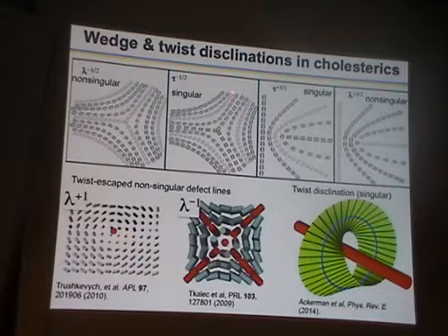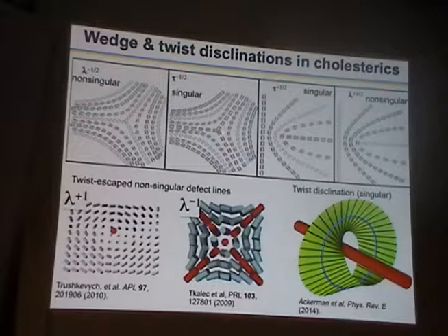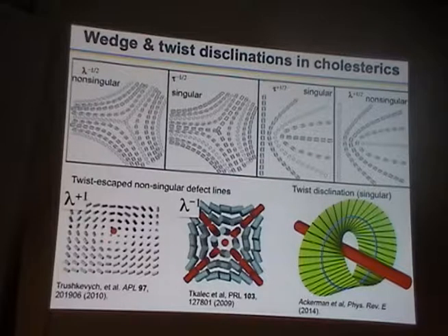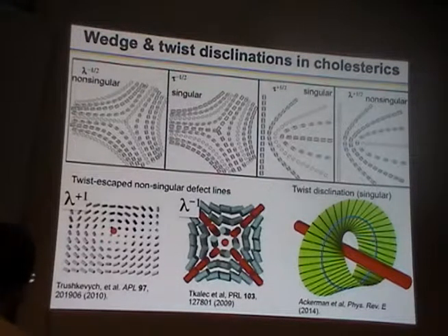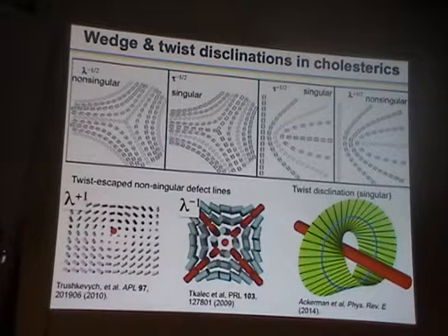Right? While the other example I'm showing here, which is tau disclination, has a singularity in the material director field. So this means you would actually have to either melt this core of disclination or form a biaxial core in order to be able to reduce free energy as much as possible, and avoid divergence of free energy.